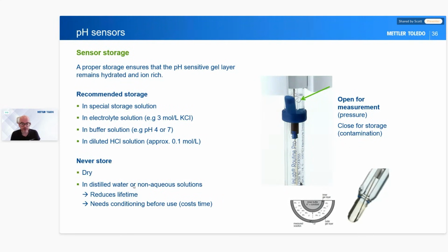The second one is we never use distilled water. If we use distilled water, the hydronium ions inside will leach out, and then it's very difficult to get them back in again and keep it ion rich to allow the flow of ions in and out. When this becomes depleted, then it won't work. So we need to make sure that we're using one of these recommended storage solutions. At worst, table salt in some tap water would be better than nothing. Then I would highly recommend you get hold of one of these solutions if you don't have one in the lab already. But never ever store it dry, never ever in distilled water.